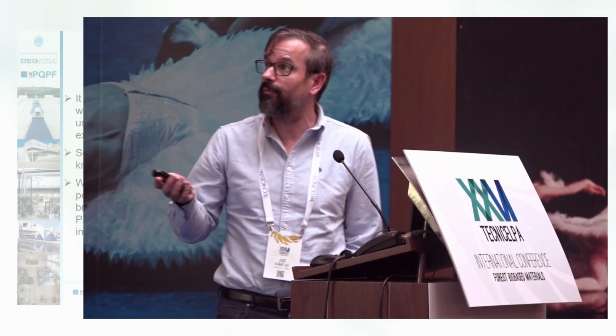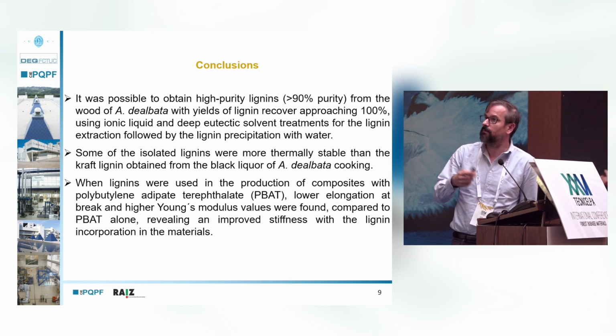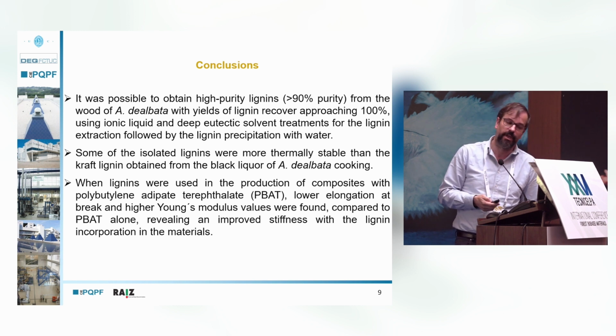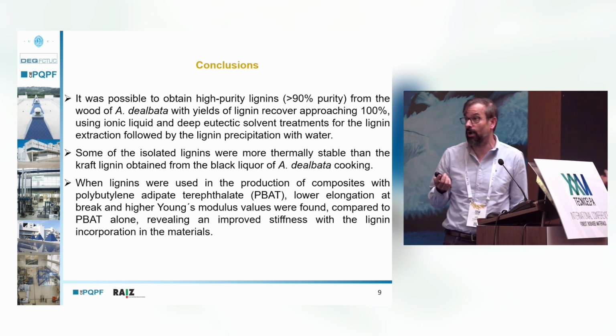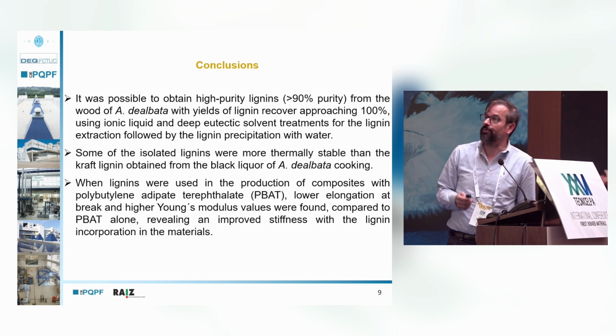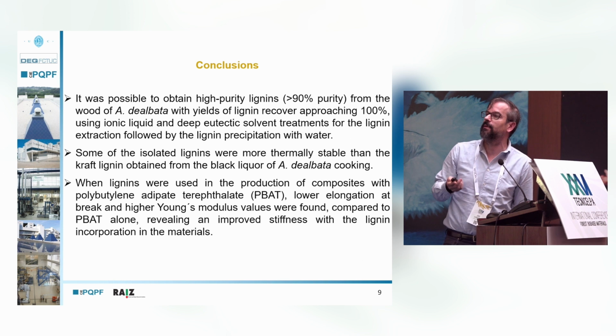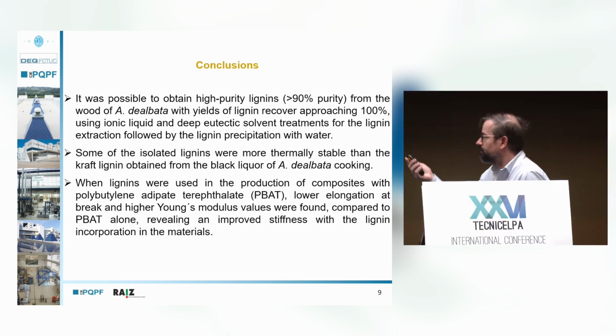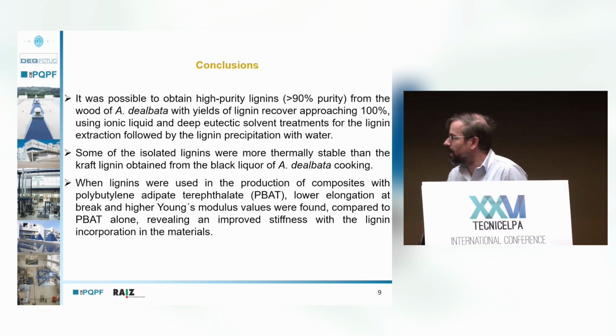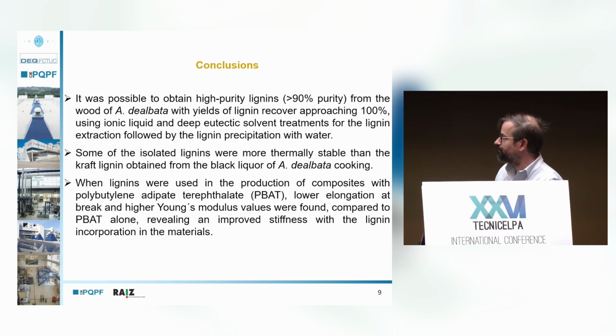Final conclusions. It was possible to obtain high purity lignins with more than 90% of purity from the wood of Acacia dealbata, with yields of lignin recovery approaching 100%, using either ionic liquid or deep eutectic solvents for the extraction of lignin, followed by the precipitation of lignin with water. So it is good, good results. Some of the lignins were more thermally stable than the kraft lignin obtained from the black liquor of Acacia dealbata cooking. However, it is not to say that the kraft lignin is worse, but it's a result. As you can see, Acacia kraft lignin is also a good option.